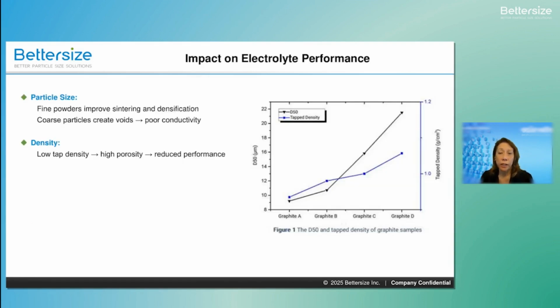Here's a study on an anode material, which is graphite. The D50 obtained from the particle size measurements versus its tap density are presented in the figure. The tap density increases with the increase of the median particle size, or the D50. The larger particles achieve higher tap densities by more effectively filling the voids between the particles, reducing the interparticle space compared to smaller particles. A higher tap density is beneficial for enhancing the battery's energy density.